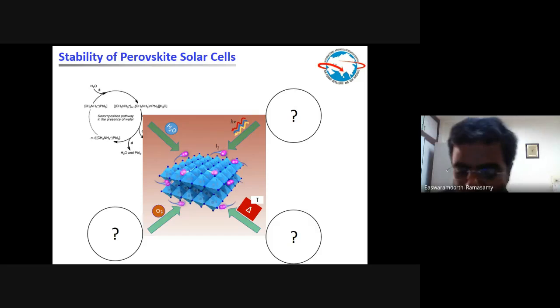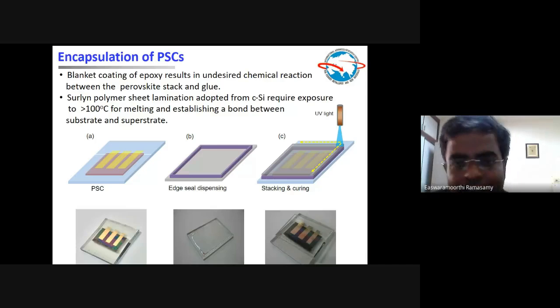So we also started very big activities on the stability of the perovskite solar cells: how the material is degrading, how the efficiency goes down, and what are the possible approaches to improve the stability of the device. First we have to make the encapsulation so that the material stability can be studied in open conditions. So we developed a low temperature encapsulation technique by using a UV curable edge sealing approach.